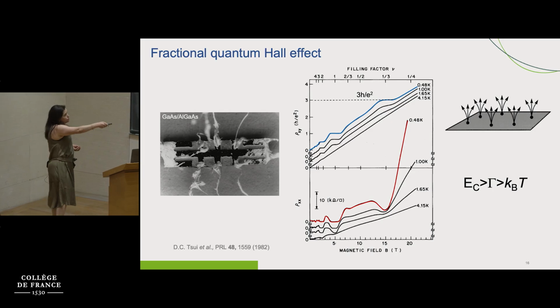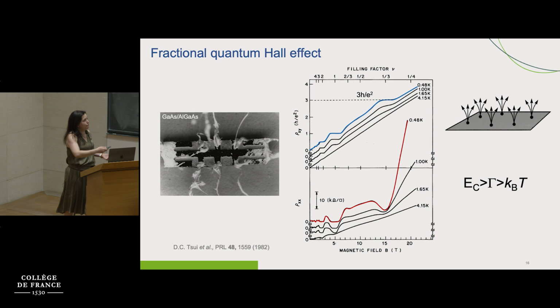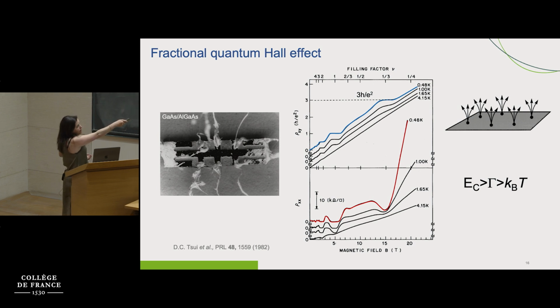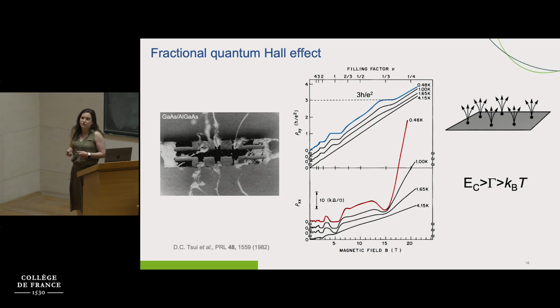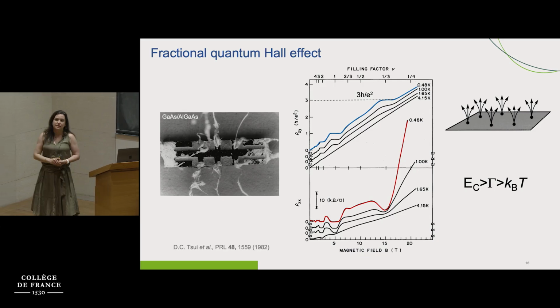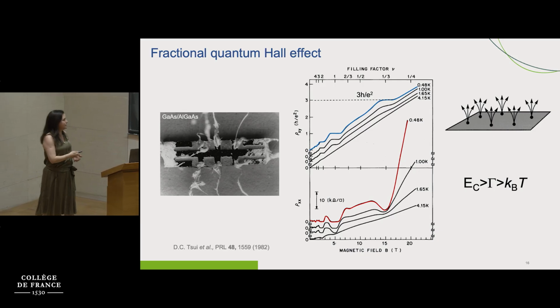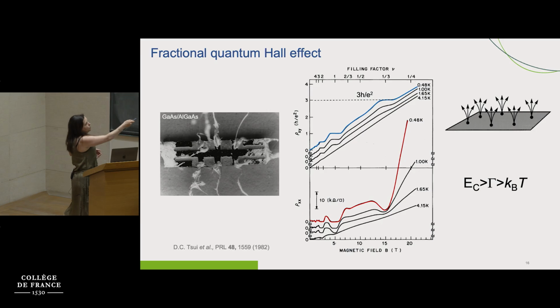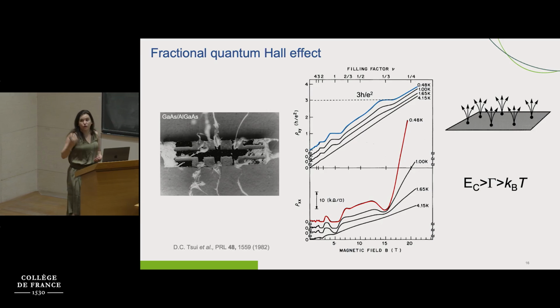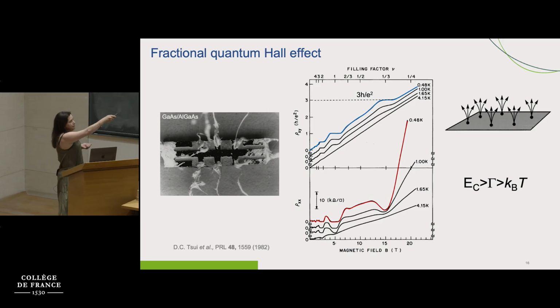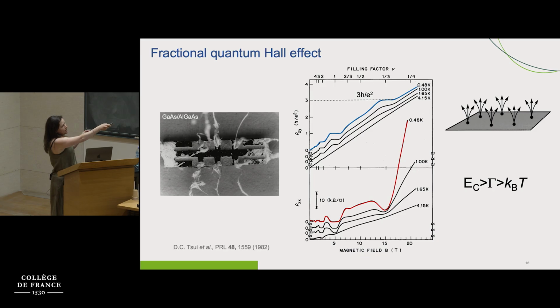So in order to obtain a fractional quantum Hall effect, which can be seen here by the quantization of the resistance, this time in terms of the same units, the same fundamental constants, but with a filling factor or a Chern number of 1/3, and that has exactly the same characteristics as the integer quantum Hall effect. A plateau in the Hall resistance, and at the same time a drop in the longitudinal resistance.